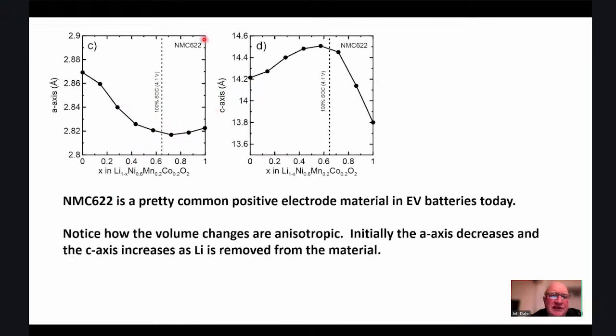So for an NMC 622 material, if you take a look at the way the unit cell parameters of the crystallographic lattice change with the lithium content, there are 2 crystallographic axes in the unit cell called A and C. And if you operate between fully discharged and 4.1 volts, the A-axis shrinks a little bit and the C-axis expands a little bit. So there's this sort of anisotropic expansion in the particles.